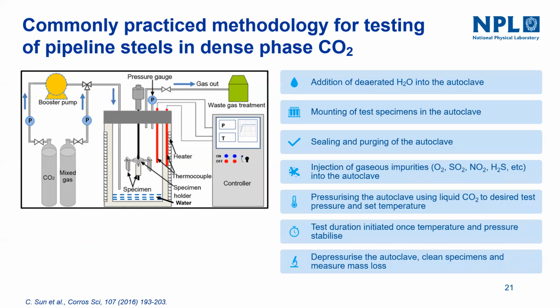Normally used for studying these pipeline steels. Water is added in the liquid state. Then the specimens are mounted, the autoclave is sealed, gaseous impurities are added, and the autoclave is pressurized to the desired test pressure and temperature, and the test procedure is initiated once it is stabilized. Normally it takes like 1 to 2 hours.